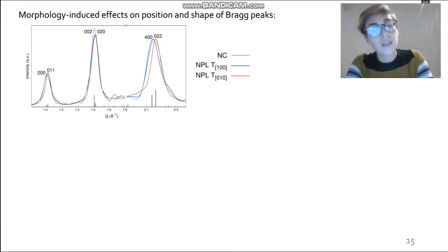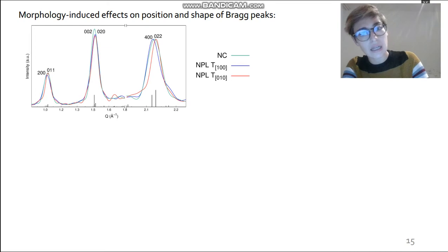For such thin plate-like nanocrystals, the diffraction signal, and in particular the Bragg peaks component, is strongly influenced by complex effects related to the combination of highly anisotropic morphology with the huge amount of diffuse scattering, which is typical of crystal domains having limited extension.